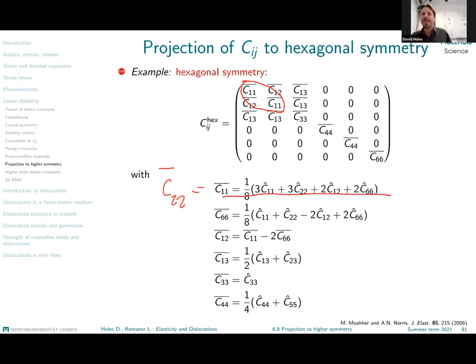Here, this projection technique yields analytically more complicated formulae, the formulae which yield a material with the desired symmetry, but closer, now measured by this Euclidean distance, closer to the original matrix of elastic constants with lower symmetry. More details on this can be found in this paper, a very nice and instructive paper with a lot of math where this is described. Could be a very nice topic for some of your presentations if you do not have a topic yet.